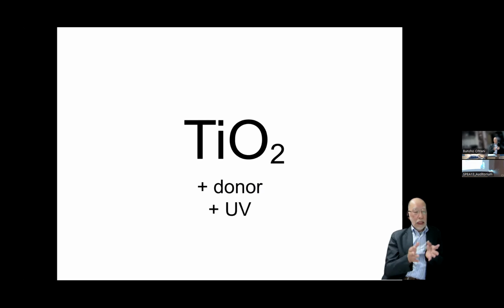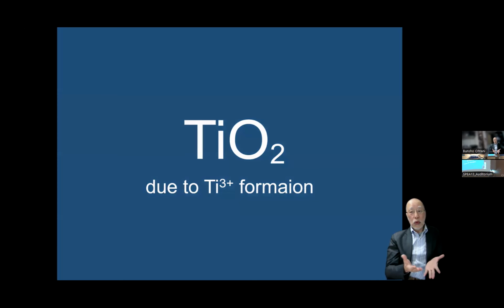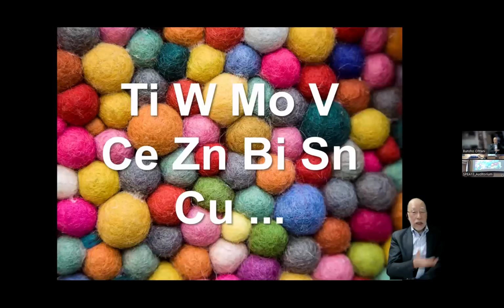Probably all of you know that titanium oxide, when UV irradiated in the presence of a donor, the white powder is converted into blue or blue-gray powder. That is due to Ti3+ formation. That means part of the Ti4+ ion in TiO2 accepts an electron to become Ti3+. So such a site accepting an electron is called an electron trap. So metal oxides, including titanium, tungsten, molybdenum, all these metal oxide powders change color when irradiated in the presence of a donor. So therefore, almost all metal oxides have electron traps.